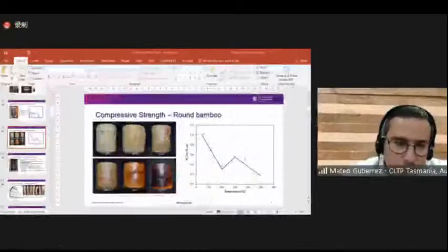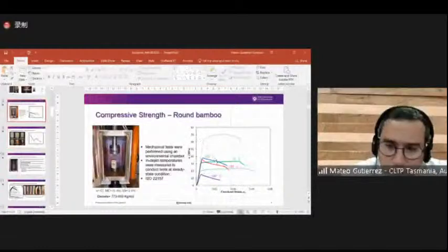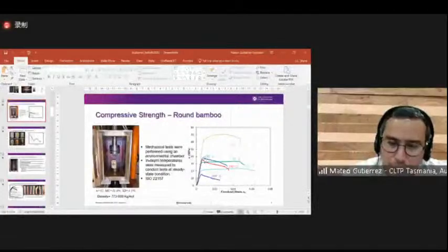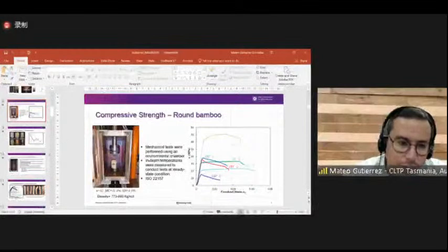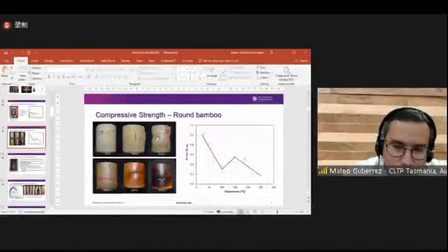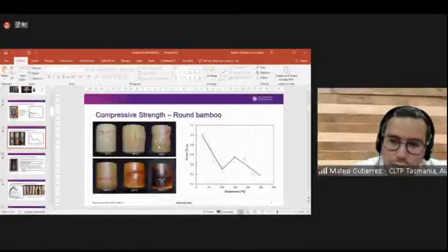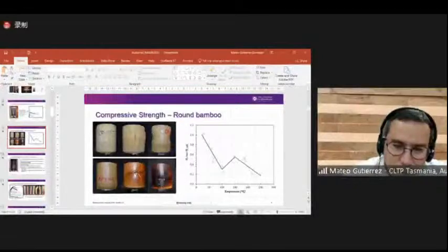Yes. So if you look at these stress strain curves here, you see that these curves have an elastoplastic behavior with a very marked elastic zone and then a plastic behavior. That's for 23 degrees, 70, and 103. But after 150, you see that the stress strain curve is different, right? And then you have something more similar to a buckling failure rather than elastoplastic failure. And if you look at the failure modes here, you see, for example, this shape at 120 degrees, when you have inwards buckling, that's quite an interesting failure mode. Whereas if you look at 200, 250, you see local buckling in the wall thickness. That's particularly for round bamboo.